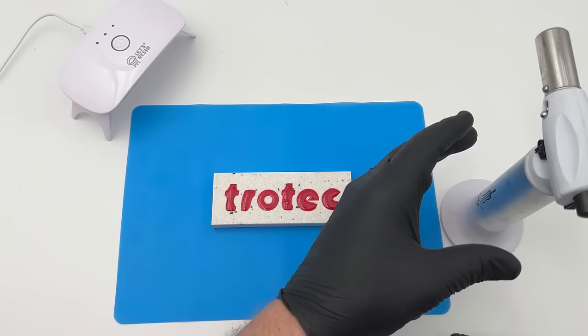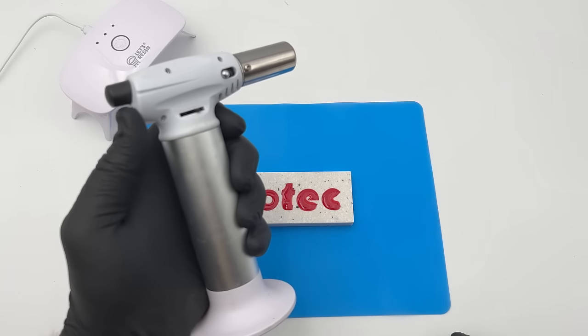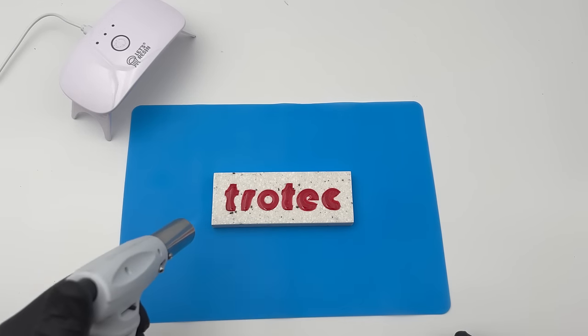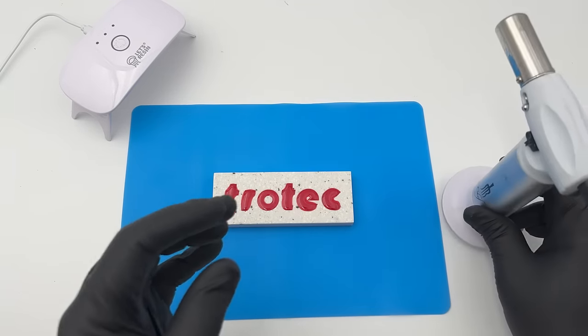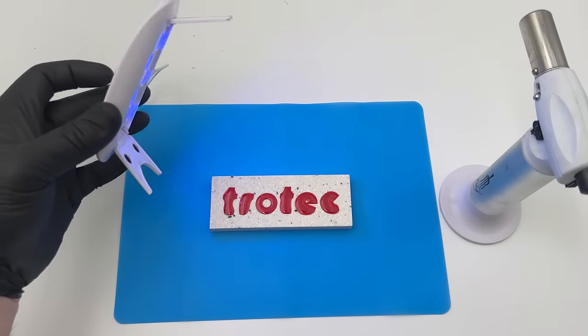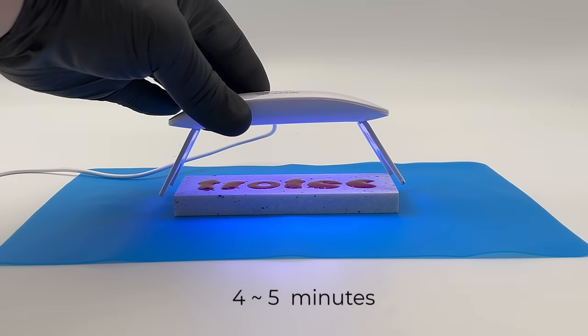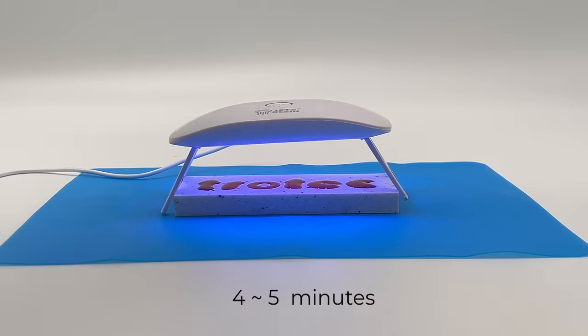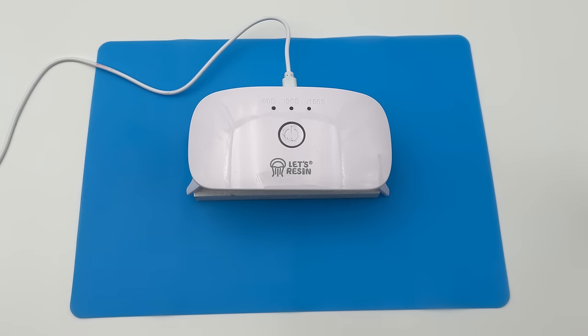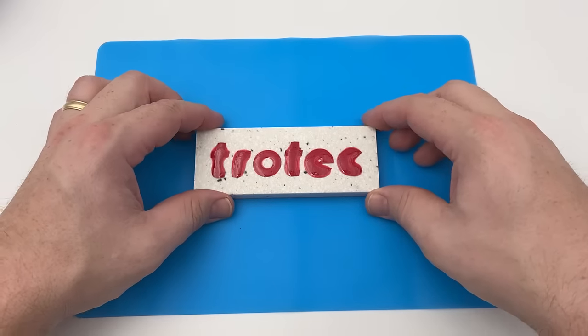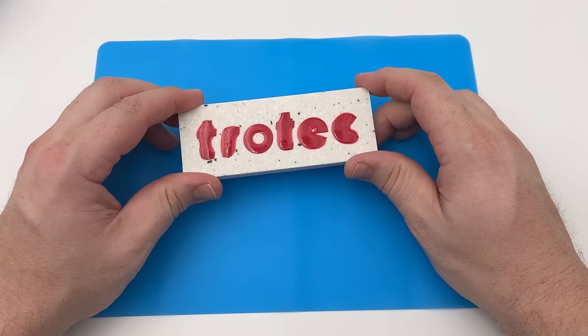Once all the gaps are filled, take the torch or a heat gun and quickly go over the wet epoxy. The heat will instantly remove any bubbles. Now, place the UV light over the part to cure it. This process only requires 4 to 5 minutes to harden completely. After it is cured, you can remove the light and it is ready for the next step.